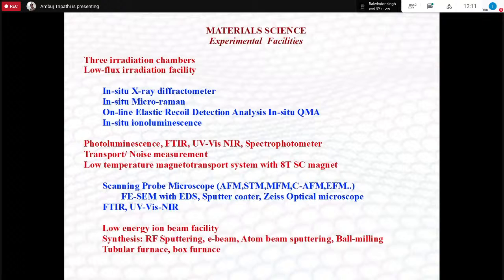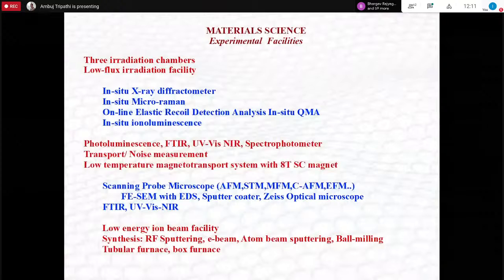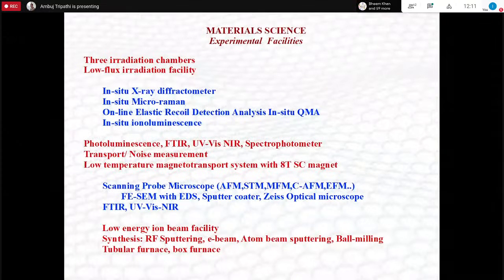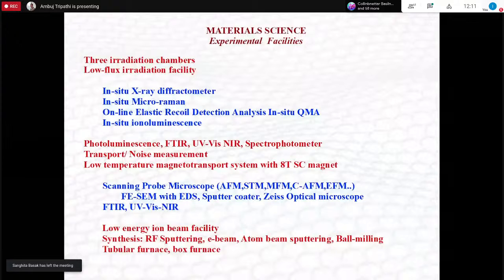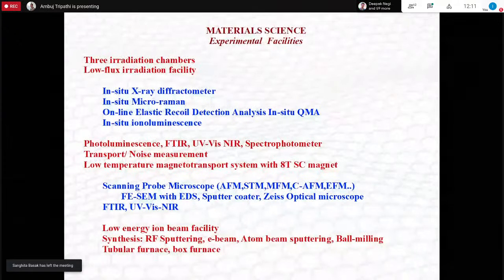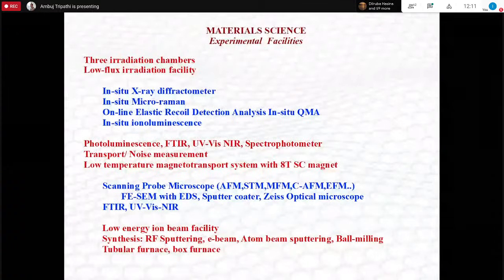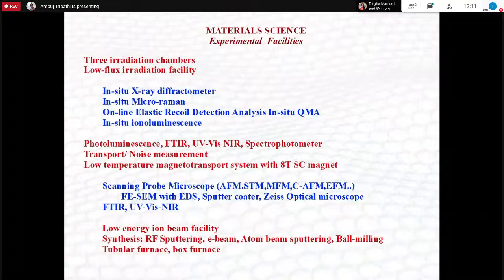So if you can afford to do it, if you don't have too many samples and you want to do a very precise measurement, you would like to do the irradiation and measurement on the same sample. You irradiate it, do the measurement, increase the fluence, do the measurement. Those types of things we refer to as in situ. Like we have in situ XRD. So XRD and Raman we have mounted in the beam lines. There you can increase the fluence and look at the XRD and Raman after this.